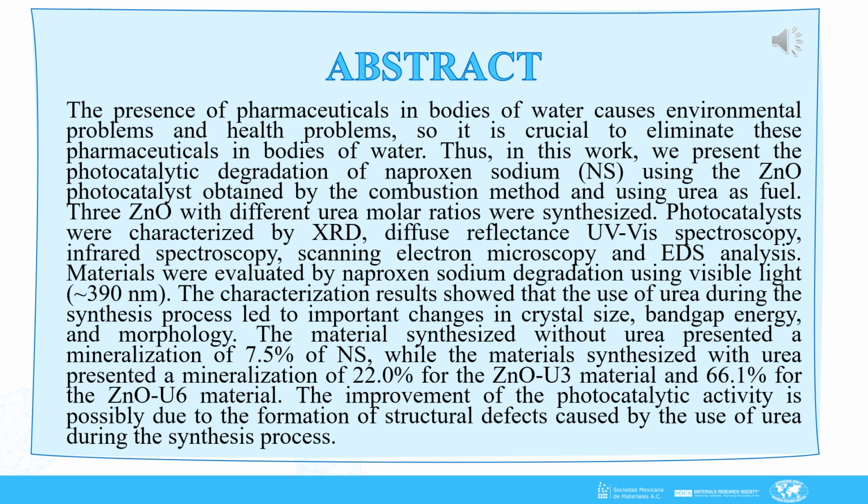We showed that the use of urea during the synthesis process led to important changes in crystal size, band gap energy, and morphology. The improvement of the photocatalytic activity is possible due to the formation of structural defects caused by the use of urea during the synthesis process.